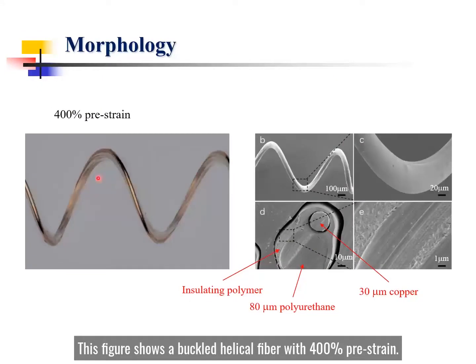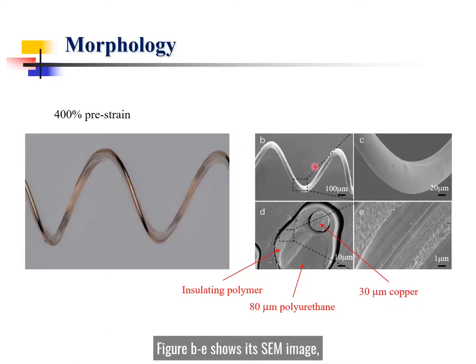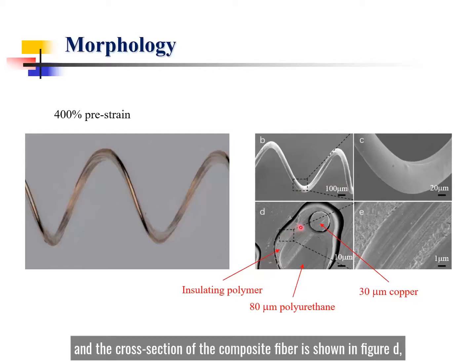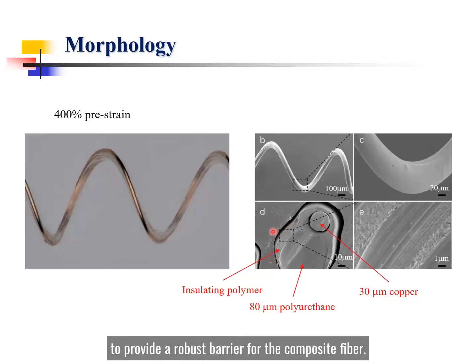This figure shows a buckled helical fiber with 400% pre-strain. Figures B to E show its SEM images, and the cross section of the composite fiber is shown in Figure D, in which the coating layer forms a uniform coating to provide a robust barrier for the composite fiber. This is in line with our expectation.